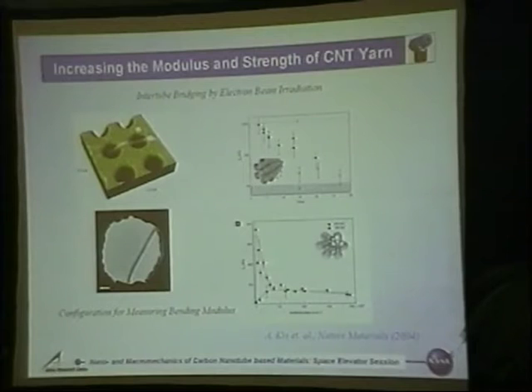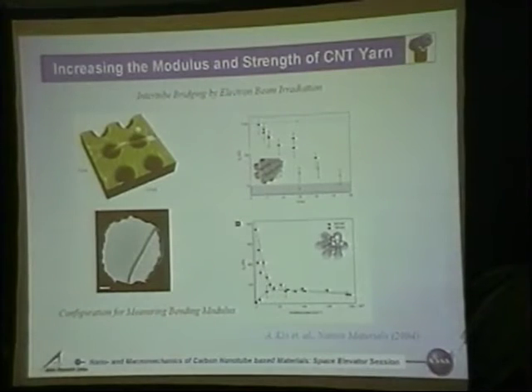So that gives you another thing, a good news part. Part of the reason it is losing the value is coming from two reasons. One is that when I scale up the material, when I take the nanotubes to make a bundle, I'm introducing these empty spaces. It's a simple geometrical construct, and that empty space reduces the volume fraction. At most, you can have 79 or 80% volume fraction because you always have interstitial space, you cannot avoid it, right? So that means you are losing because of that. Second is that your load transfer between these materials is not perfect. So for these two reasons, you lose value.